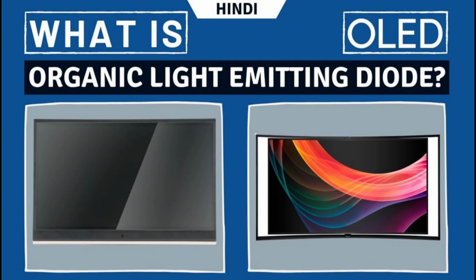One major challenge for OLED displays is the formation of dark spots due to the ingress of oxygen and moisture, which degrades the organic material over time whether or not the display is powered. In 2016, LG Electronics reported an expected lifetime of 100,000 hours, up from 36,000 hours in 2013. A U.S. Department of Energy paper shows that the expected lifespans of OLED lighting products goes down with increasing brightness, with an expected lifespan of 40,000 hours at 25% brightness, or 10,000 hours at 100% brightness.